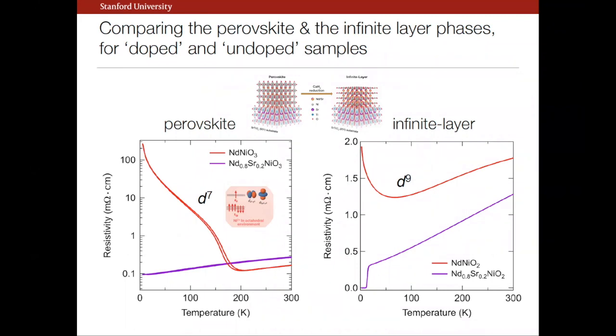So to talk through what we find, let's first look at the perovskite version. So this is the undoped neodymium nickelate perovskite. This is again this famous first order phase transition for this d7 electronic configuration. And by doping, it looks metallic all the way down. And by now taking one of the oxygen out in these planes, we go to a nominal d9 configuration, where in the undoped case you have this weak upturn at low temperatures, and in the doped case we see a superconducting transition.